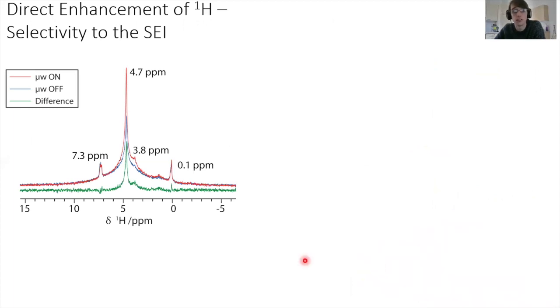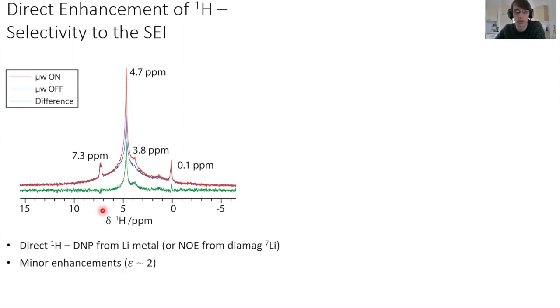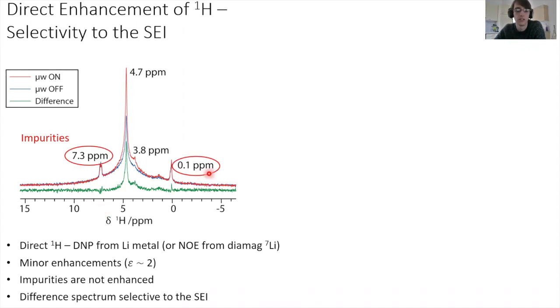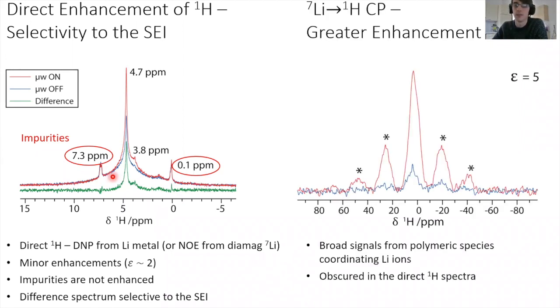We also looked at protons. So in the proton NMR, this is a direct spectrum, just protons with and without microwaves. We get enhancements. They're pretty minor, around a factor of 2. But again, the impurities aren't enhanced, and so this is giving selectivity. And if we take a different spectrum, we have a spectrum that's just of the SEI near that interface. You can also do cross-polarization experiments from lithium to proton, and this gives you larger enhancement, and it's sensitive to polymeric species that coordinate lithium ions that are very broad and hard to see in the direct spectrum.